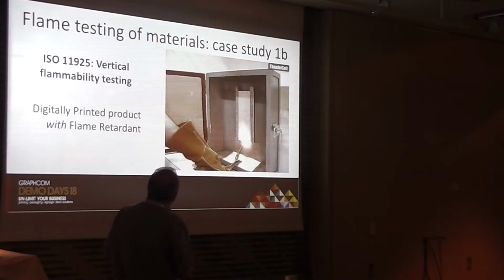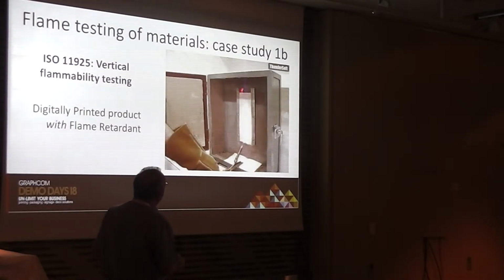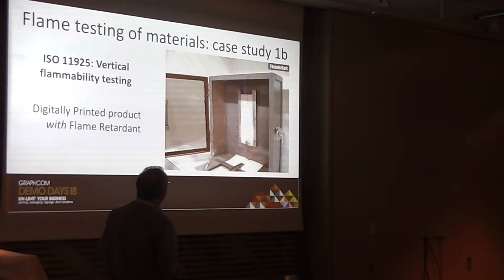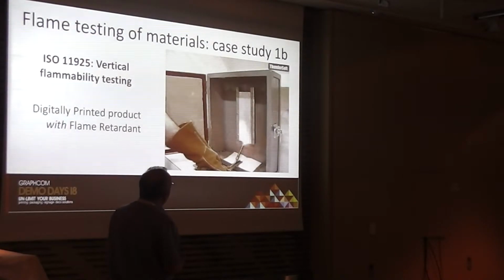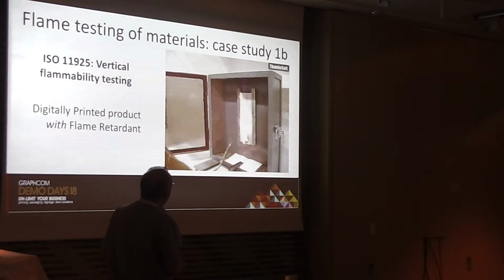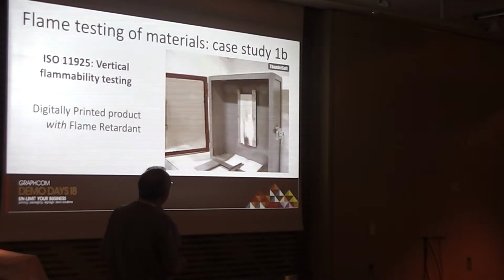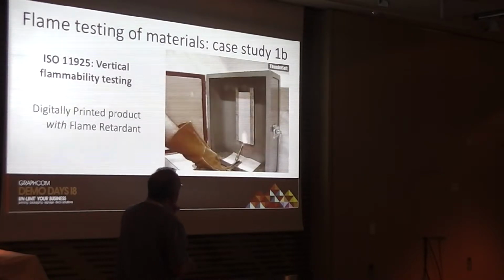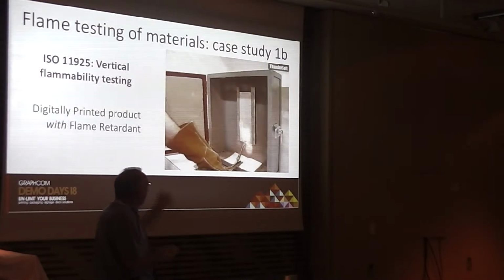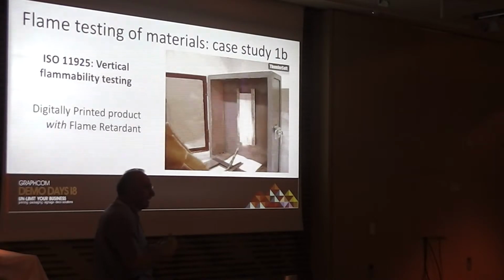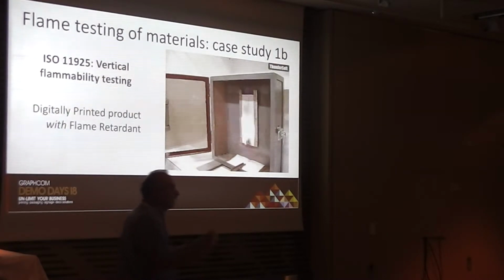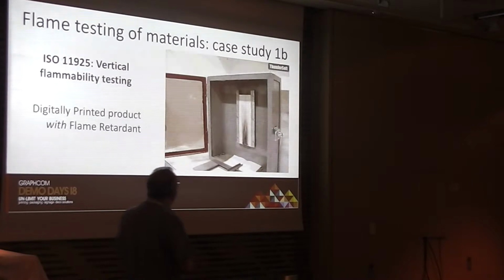There. Now this one here is the same, but applying a flame retardant on the front surface of the product. It was a printed card, and you can see that the flame retardant has a very good effect. Once you remove the flame, the fire actually goes out on its own. So it worked. But this illustrated that the paper, it was actually cardboard, did have flame retardant properties, but once you put the ink on, it changed. So you had to change that.